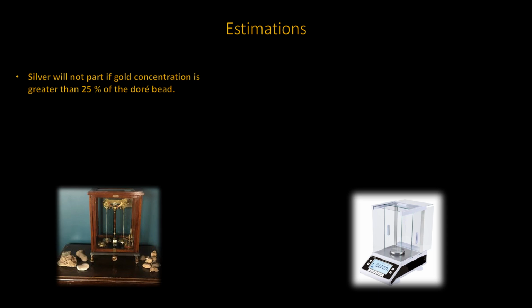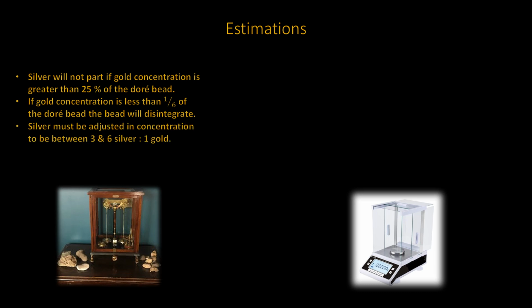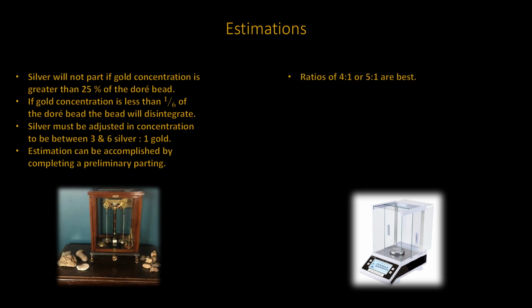Any gold concentration in a bead that is greater than 25%, or 1/4 the weight of the bead, silver will not part. Silver must be added. Any gold concentration that is less than 1/6, or 16%, the silver concentration is much higher, and the bead will disintegrate. The silver concentration must be adjusted to give a ratio of silver to gold between 3 and 6 to 1. The aim is usually 4 or 5 parts silver to 1 part gold for best results.